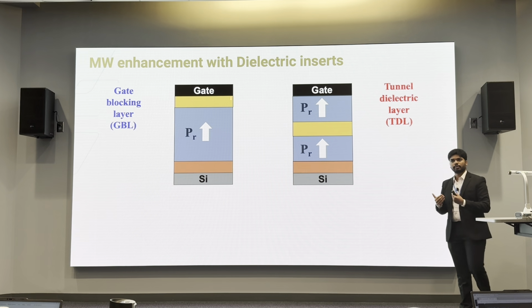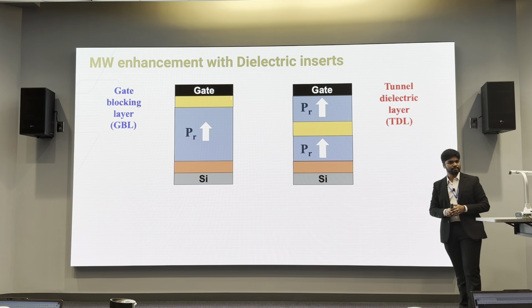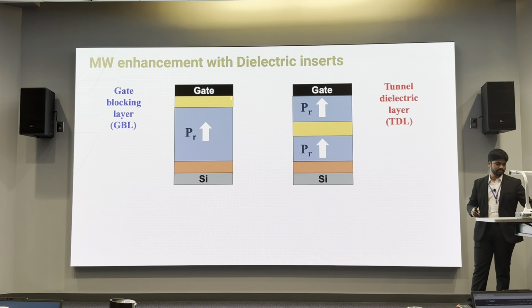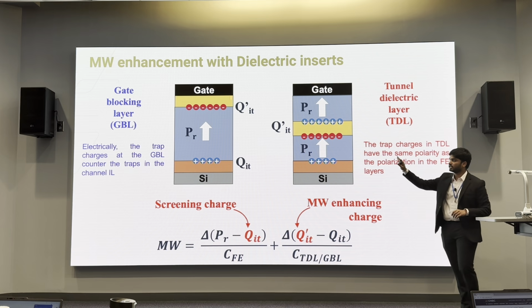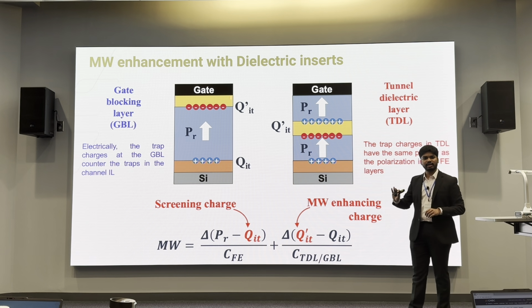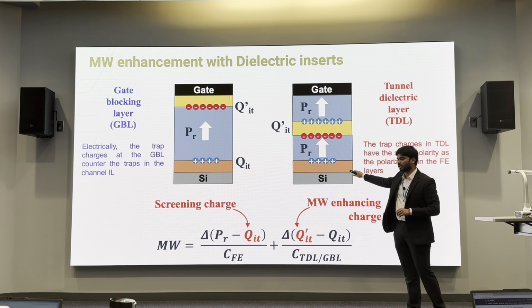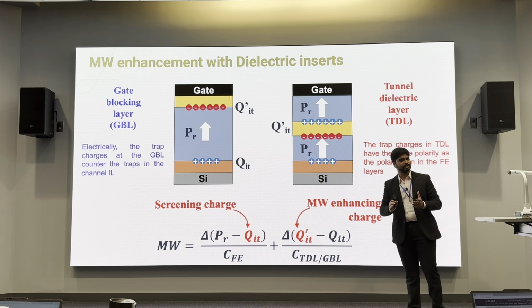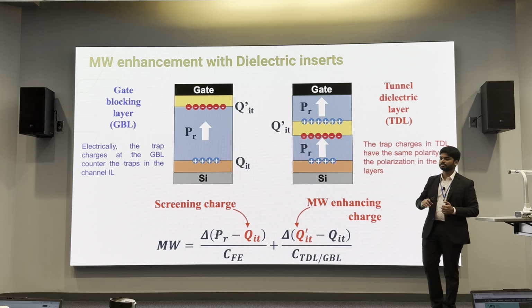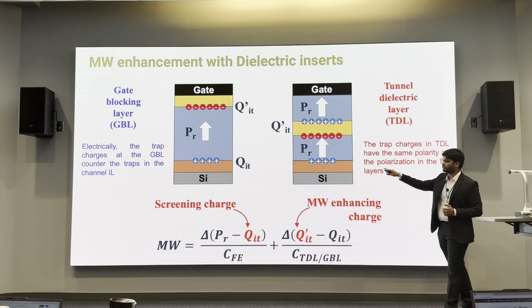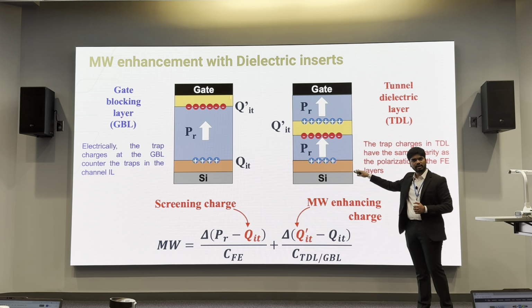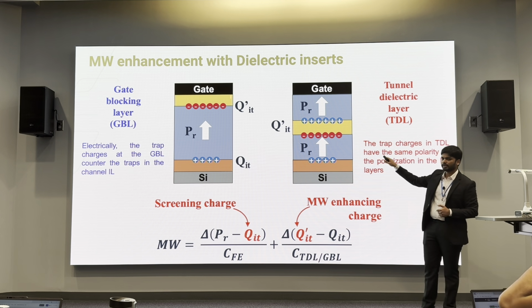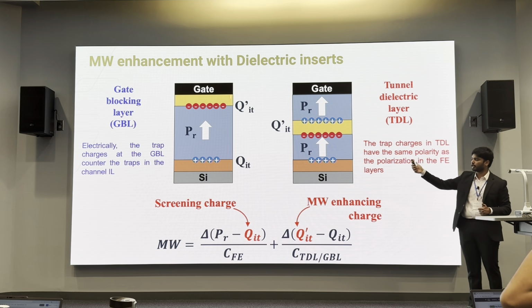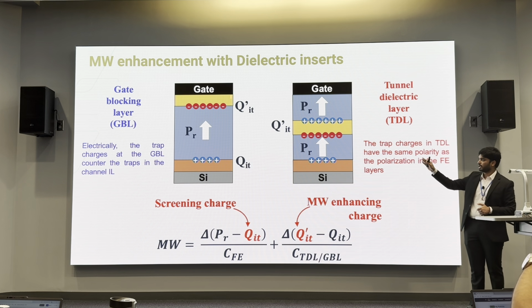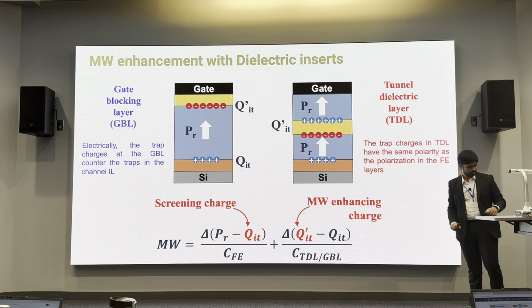Okay, you might ask where we got this huge improvement in memory window from. The current working theory is that we have trapped charges at the ferroelectric dielectric interface. Unlike the trapped charges at the ferroelectric silicon dioxide interface, which are detrimental as they screen the ferroelectric polarization, the charges that sit far away from the channel IL boost the memory window either by amplifying the ferroelectric polarization or by forming a dipole.